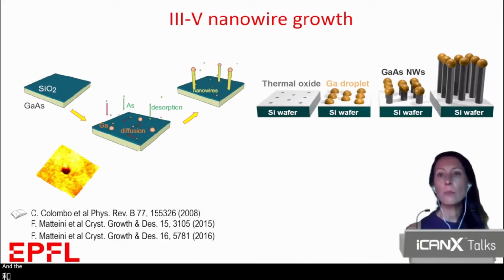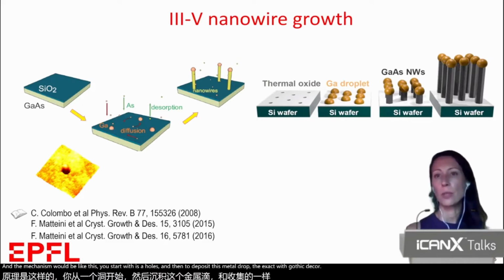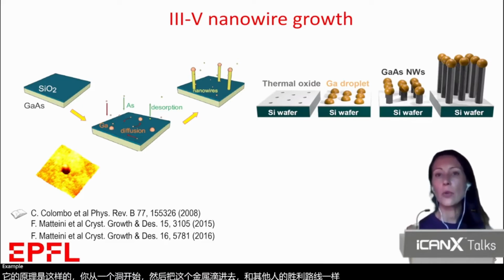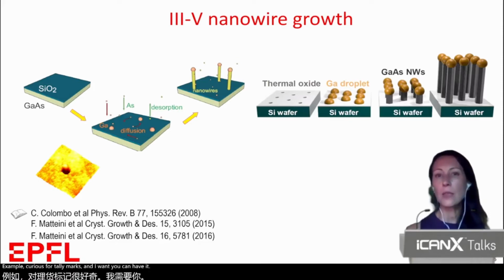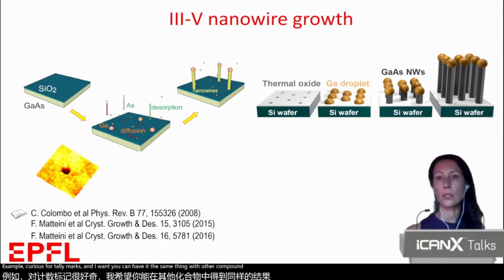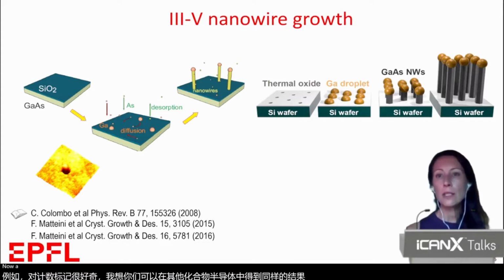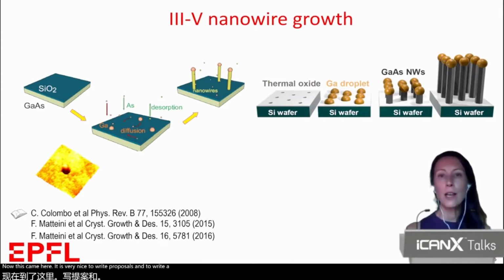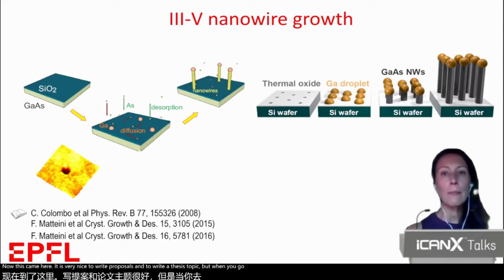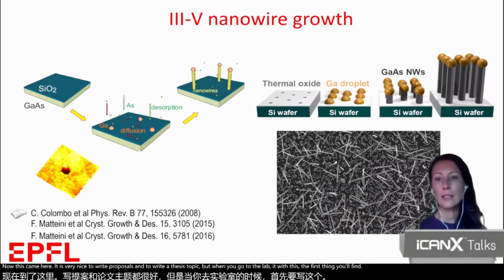And the mechanism would go like this. You start with these holes, and then you deposit these metal droplets that will gather the growth precursors. The example here is for gallium arsenide, but you can have the same thing with other compound semiconductors. Now, this scheme here is very nice to write proposals and to write a thesis topic, but when you go into the lab and do this, the first thing you find is this thing here.